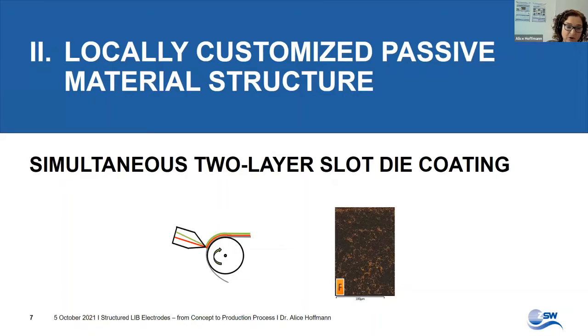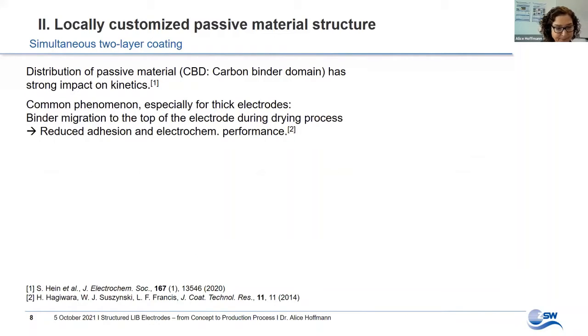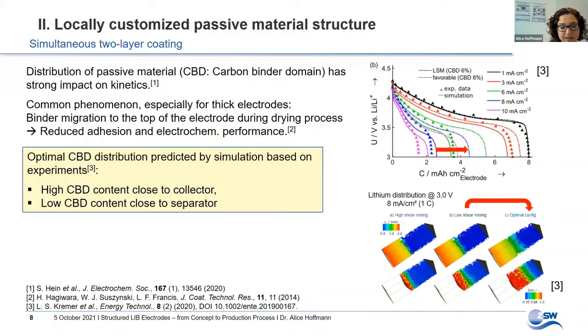The next concept I want to show is a locally customized passive material structure reached by simultaneous two-layer slot die coating. In the electrode composite, the distribution of passive material, designated as carbon binder domain, has a strong impact on the kinetics. Simulation combined with experiments suggested an optimal CBD configuration for high power in ultra-thick cathodes. It consists of a high proportion of CBD close to the current collector and a lower proportion close to the separator. Compared to other CBD structures, for this configuration less lithium depletion and a higher active material utilization, and consequently an increased areal capacity, was predicted at a discharge rate of 1C.